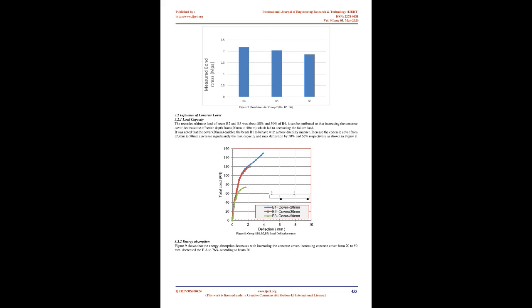The load was divided into 2 concentrated loads 1500 mm apart, at the cantilever free end and beam midspan, using a rigid steel spreader beam. The actuator was driven in displacement control and the load was applied against a reaction steel frame. Data from load cell, dial gauges, strain gauges, and extensometer were recorded manually during the test.